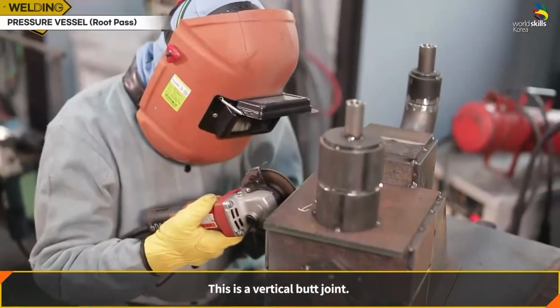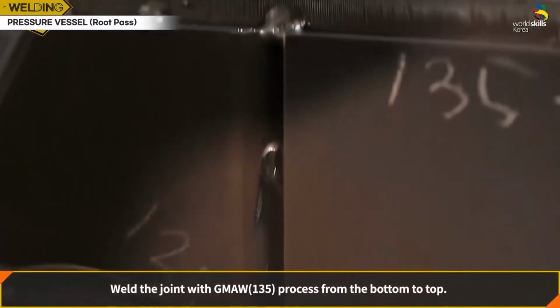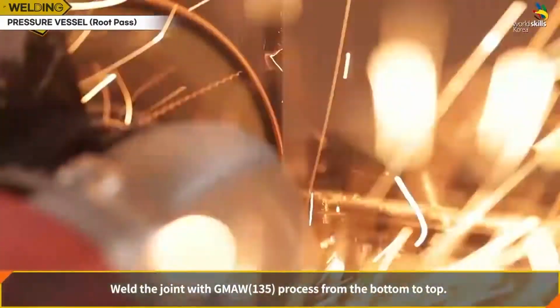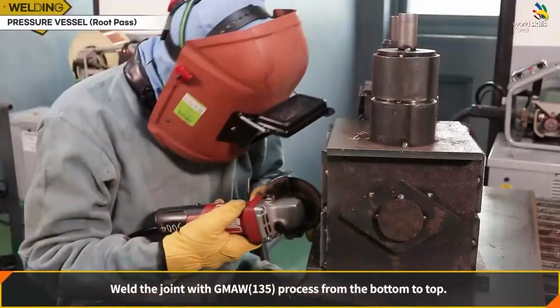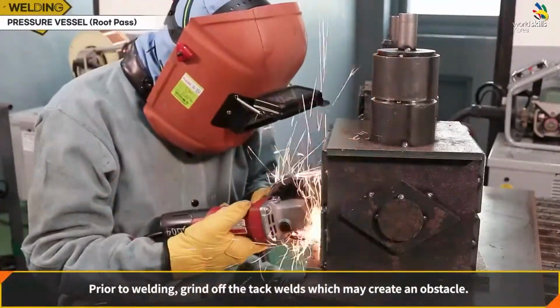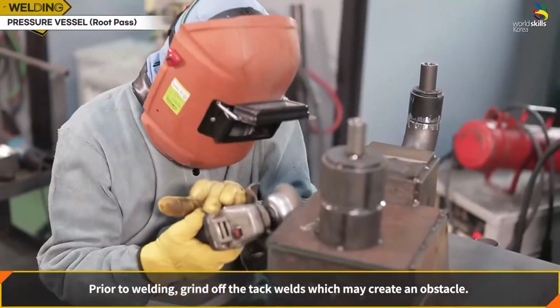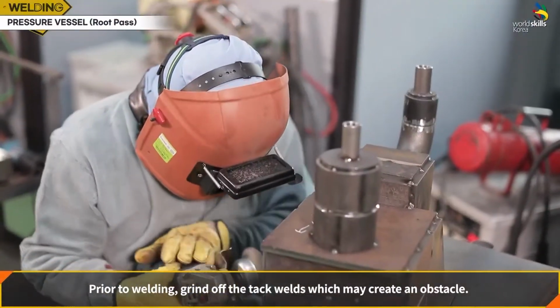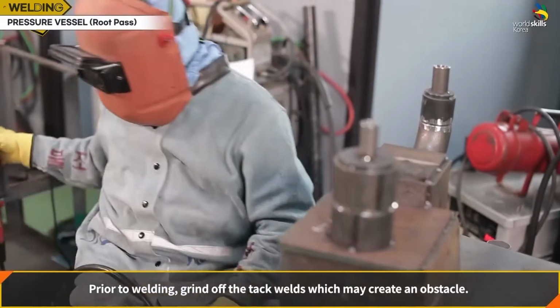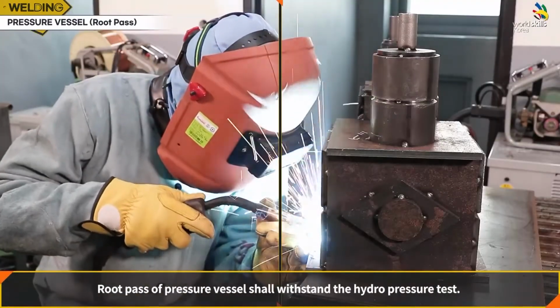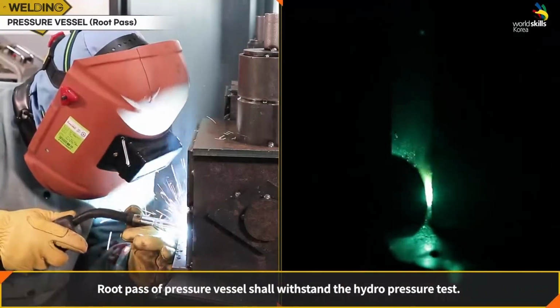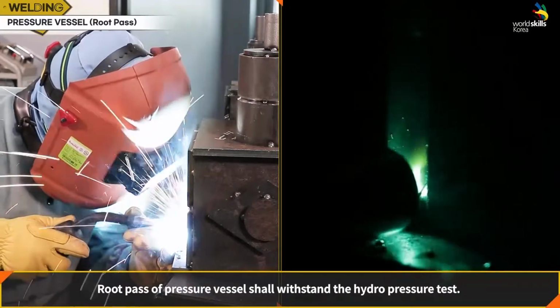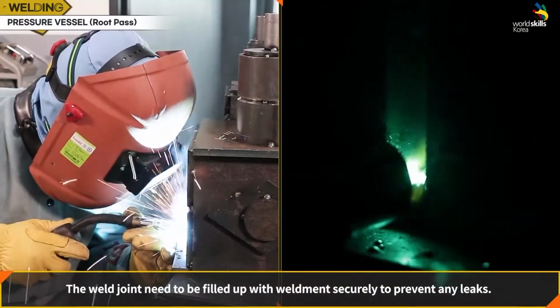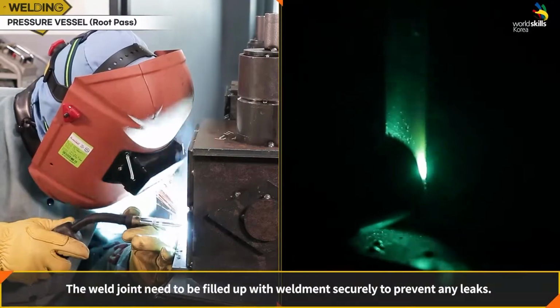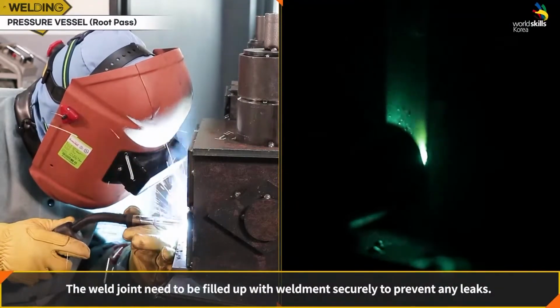This is a vertical butt joint. Weld the joint with GMAW 135 process from the bottom to top. Prior to welding, grind off the tack welds which may create an obstacle. Root pass of pressure vessel shall withstand the hydro pressure test. The weld joint needs to be filled up with weldment securely to prevent any leaks.